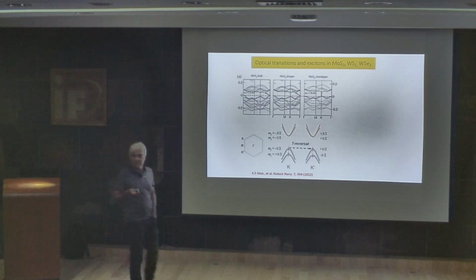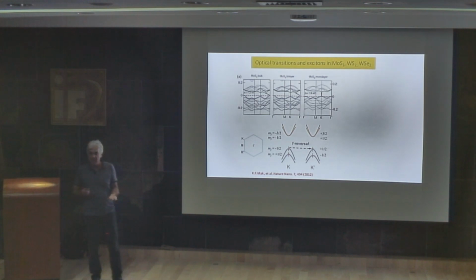Silicon is an indirect semiconductor, and silicon is very good for making devices, but it's not good for optics, because silicon is not good for making lasers or things like that. But in the case of monolayer MoS2, what happens is that now the top of the valence band coincides with the bottom of the conduction band. Then we have what we call a direct gap semiconductor.